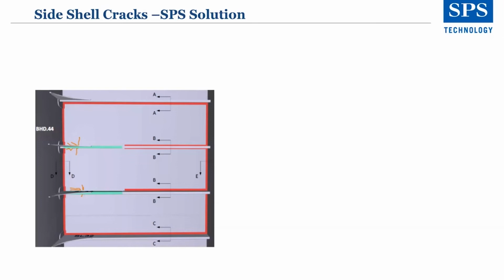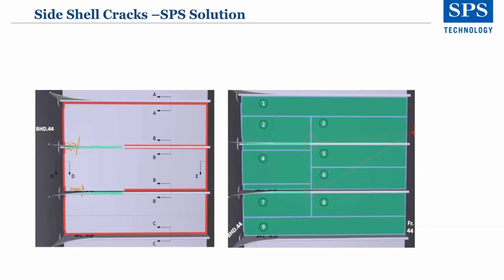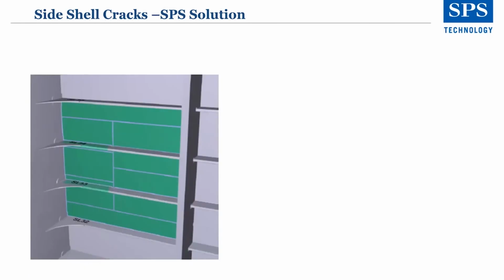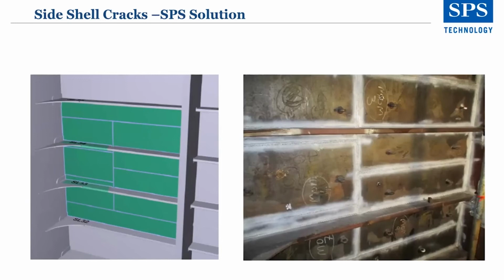We apply moisture tolerant sealant and structural sealant over the cracks to stop any moisture coming through. We fit and tack backing bars, as you can see in red, around the perimeter of the area, including top and bottom of the web frame. Once that's in place, we then position plates on top of those backing bars, creating a seal cavity. Once the seal and the welds have been put into position, you have one formed cavity where the cracks are now inside, although behind the longitudinal stiffeners, they're inside that seal cavity.